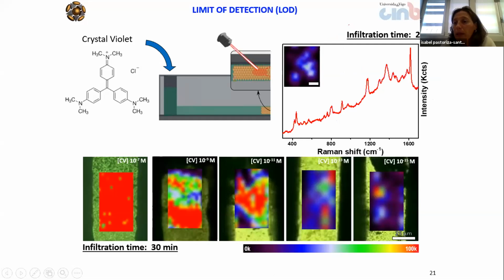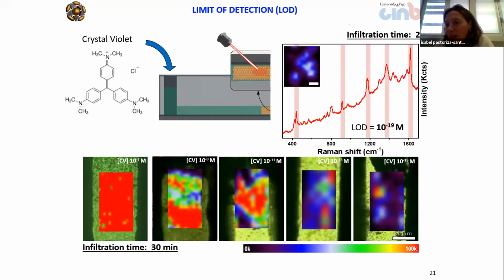But just by increasing the infiltration time, we are able to improve this limit of detection. For instance, we can get 10 to the minus 19 molar with an infiltration time of 24 hours. Of course, this is not really practical or really good for a real application.